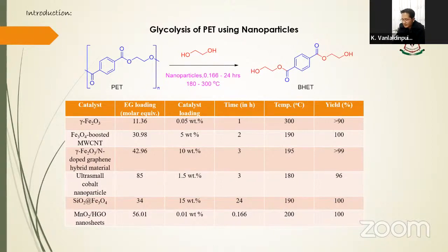See, most of them give excellent yield. Here, the lowest is 90%. The rest are 100, 99, 96%, like that. So when we use gamma ferric oxide, this is gamma ferric oxide, okay? The reaction was completed within 1 hour, but the reaction temperature is 300 degrees Celsius. It gives more than 90% yield.